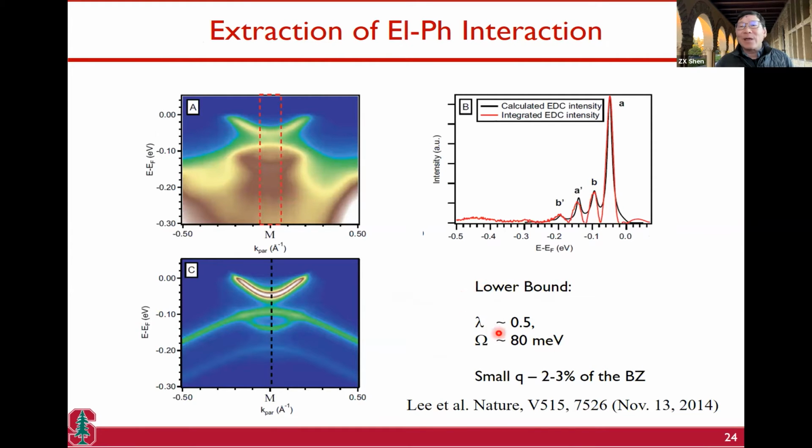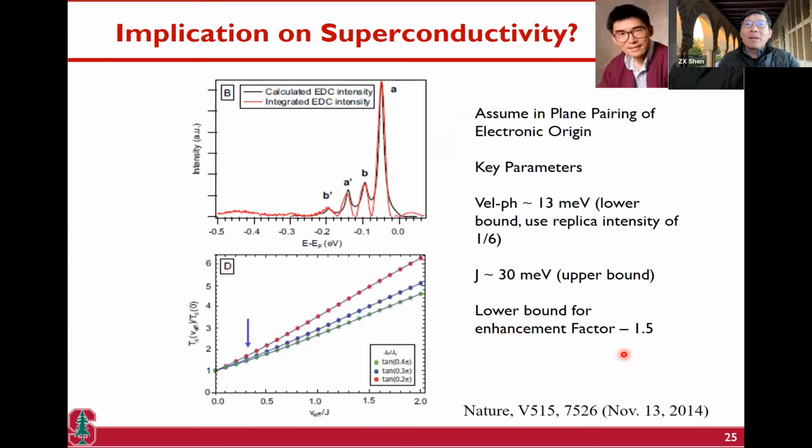This is the reason why this plays a role in enhancing TC in this way. That's their original work. One of the key things I want to stress is that this analysis really shows that it's small-Q forward scattering phonons, just like a capacitor in this sense. Now, Dung-Hai Lee and Tom Devereaux's group have done more analysis.